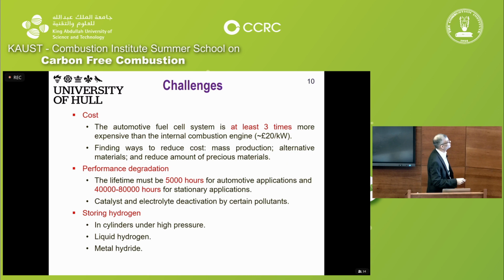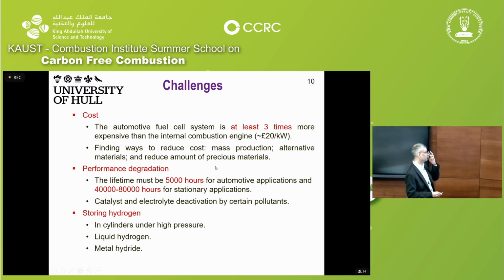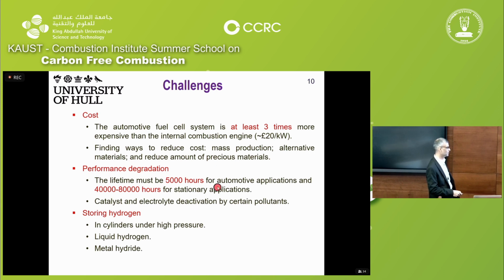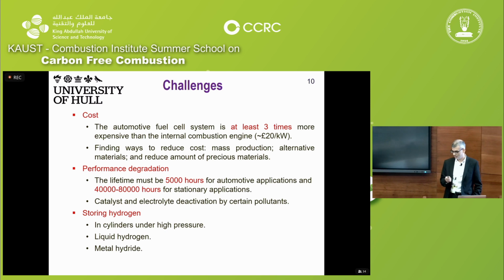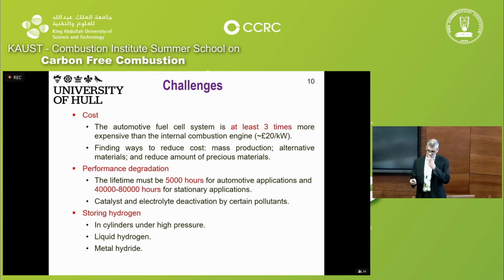Moving on, the second challenge is performance degradation. According to the US Department of Energy, the lifetime should be 5,000 hours for automotive applications and 40 to 80,000 hours for stationary applications. However, the real numbers are significantly less, and this is mainly because of the degradation associated with the catalyst and the electrolyte. For example, as mentioned in the first presentation, platinum catalyst is very, very sensitive to carbon monoxide. Only a few parts per million of carbon monoxide could kill the catalyst, and you wouldn't have an operational fuel cell.